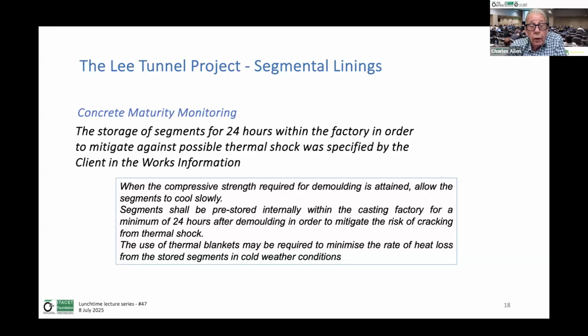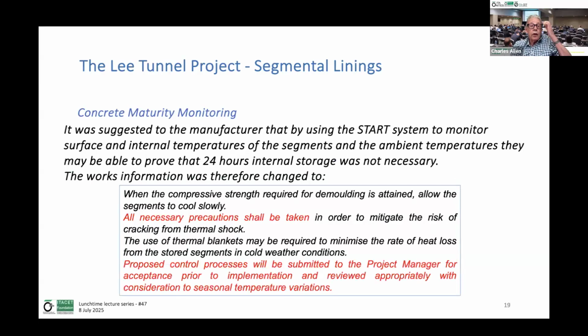The issue with that was we had a relatively small factory, and to store 24 hours of production inside the factory was really taking the factory to its limits. So it was suggested to the manufacturer that by using the maturity monitoring system to measure internal temperatures and surface temperatures and the ambient temperatures, they might be able to prove that 24 hours internal storage was not necessary. So we changed the specification to allow proposed control processes that will be submitted to the project manager for acceptance prior to implementation and reviewed appropriately with consideration to seasonal temperature variations.